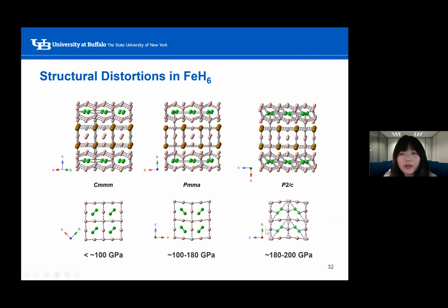The difference between these three phases is that in the Cmmm structure, the projected view looks like almost squares, and the molecular hydrogens are parallel to each other. In the projection view of Pmma, the atomic layers are slightly distorted, and every second molecular hydrogen is rotated 90 degrees along the a direction. For the P2/c structure, the atomic hydrogen layers are further distorted, and now in the projected view, the neighboring layers are no longer on top of each other. So at higher pressures, the distorted phases are preferred.